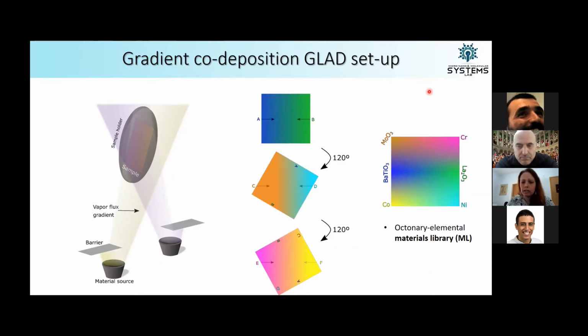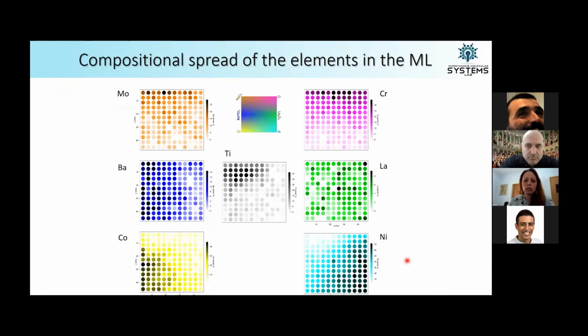And these sort of materials were actually chosen because they each individually show activity towards oxygen evolution reaction, which was the system that we wanted to study for this material library. So just from looking at a composition point of view, you can already see that there's high compositional changes throughout the library with the different materials coming off the different edges. So for the nickel corner, or nickel edge, where the nickel starts, the highest compositional element is nickel, cobalt, etc., and so on. And they're really spread out quite nicely from a compositional point of view.